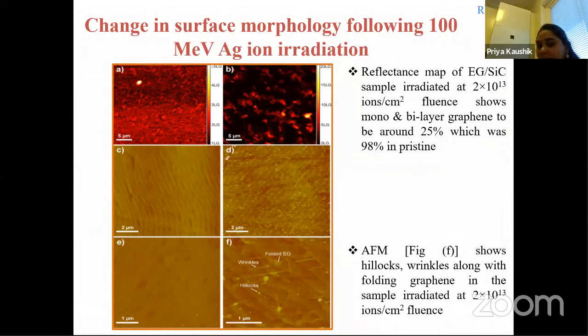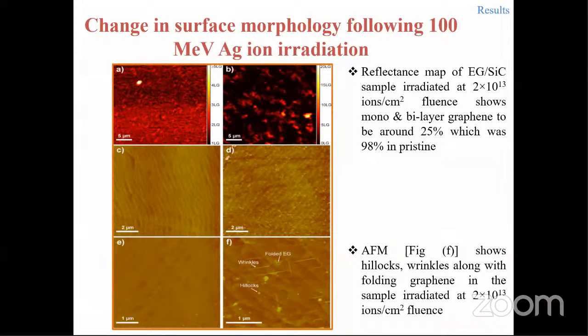And when we have done 100 MeV ion irradiation on it, we have observed that 98% monolayer graphene is reduced to 25% monolayer graphene. And this occurs because of foldings in graphene. There are multiple foldings in graphene.